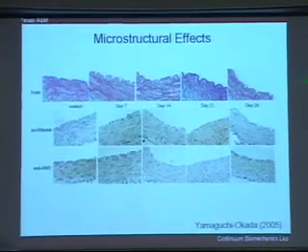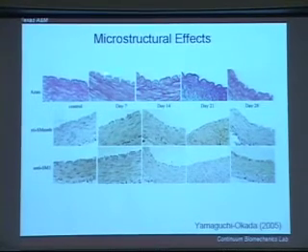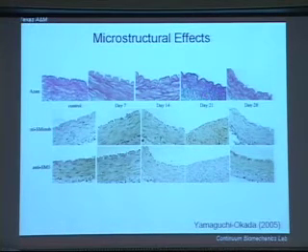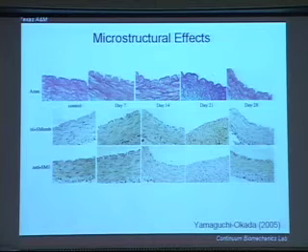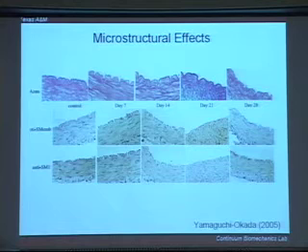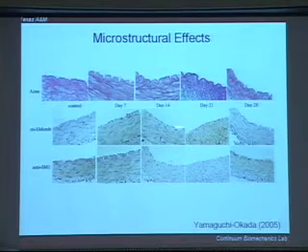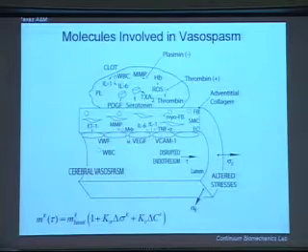If you look at the normal histology, the main thing to point out here is at day 21 versus control. The pink is largely smooth muscle. You see a normal media. Here what we see is a lot of blue, and in this particular stain, that's showing new collagen that's been produced. So as this vessel constricts down, there's new collagen production, again at a much heightened rate because of this chemostimulus. Here immunohistochemistry shows a transition from a more contractile smooth muscle phenotype to more synthetic, the brown staining consistent with the collagen deposition, and then here the converse, with the return back to the contractile phenotype after 3 weeks.